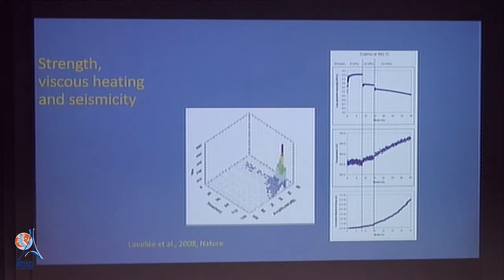And so on the right-hand side of the diagram, at the top, you have 3 different values of the stress sustained by the sample as a function of the different loads that you see listed up there. You see that the first 2 are leveling off to a viscosity which is constant. In the third case, the viscosity is beginning to collapse. You see a line which is going straight down to the right. The reason it's collapsing is that the viscous heating has now become significant enough.